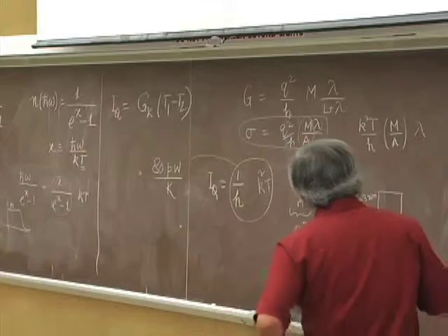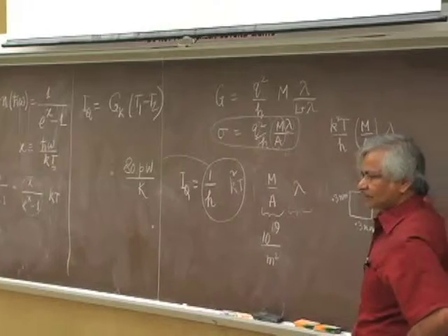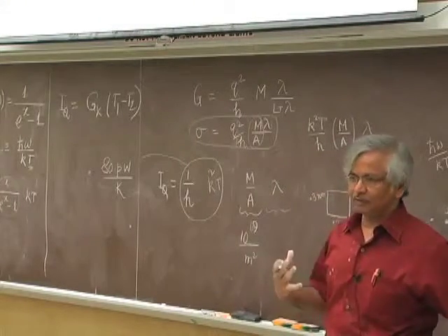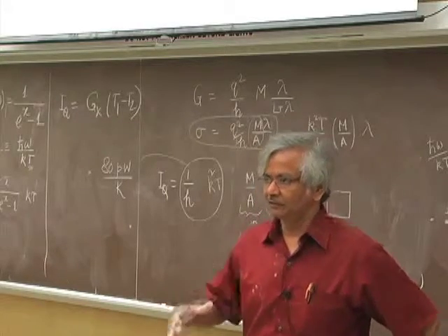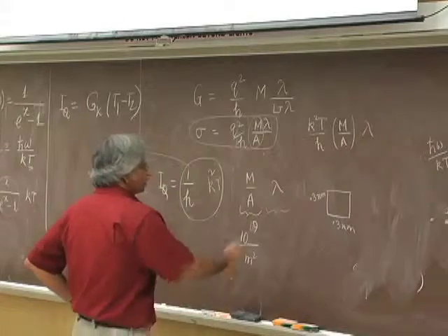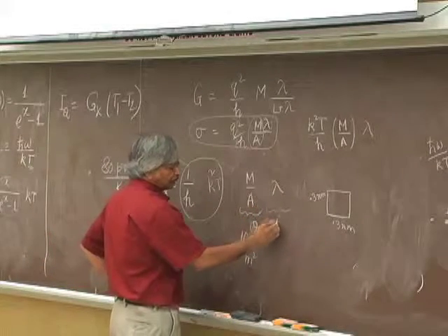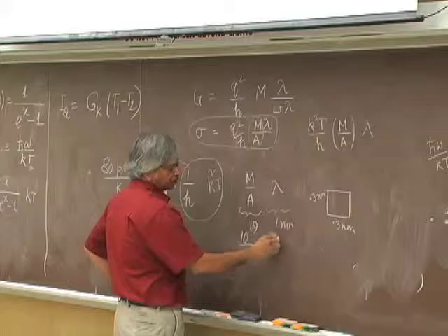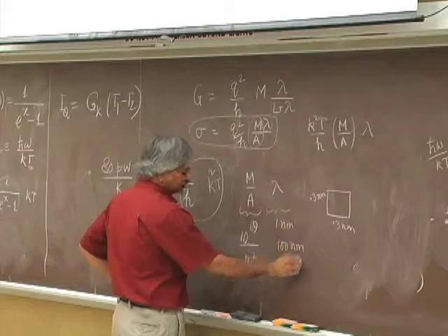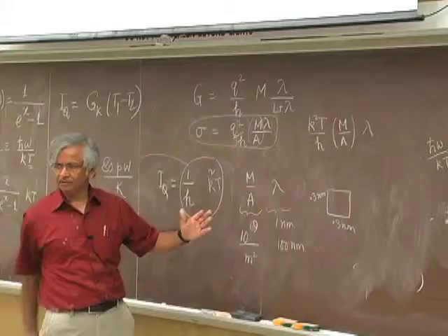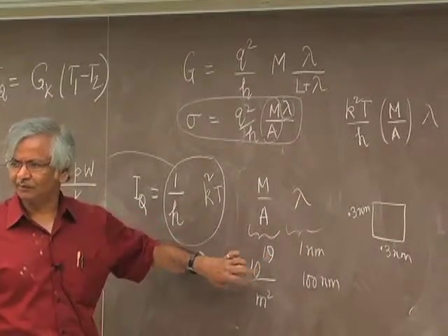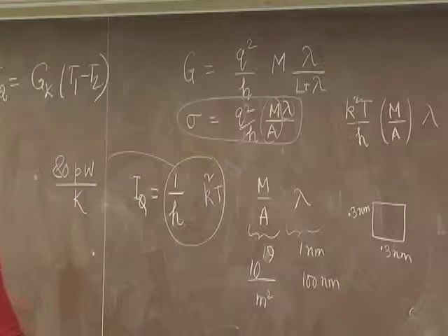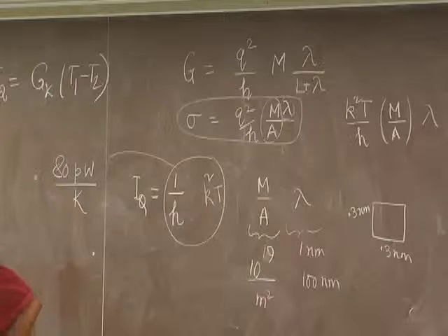And those are usually the best ones, those with very low mean free paths. You try to use materials where the phonons have very low mean free paths because of various grain boundaries or other reasons inside. And so then this can be, say, even 1 nanometer, or it can be much longer, 100 nanometers or so. A lot of the difference in thermal conductivity that you see between materials is because of this big difference in lambdas, not so much because the number of modes changes widely. There isn't quite the equivalent of metal versus semiconductors that I've seen. It is more that they're all basically like metals as far as modes go.